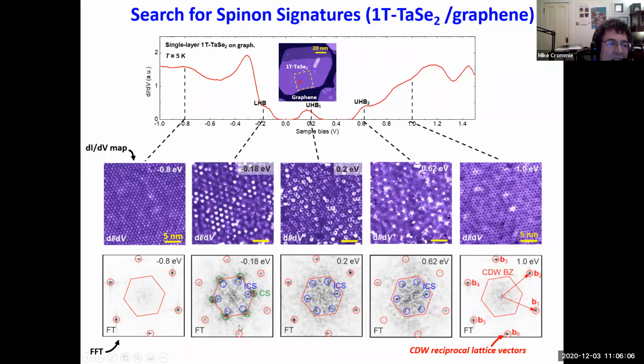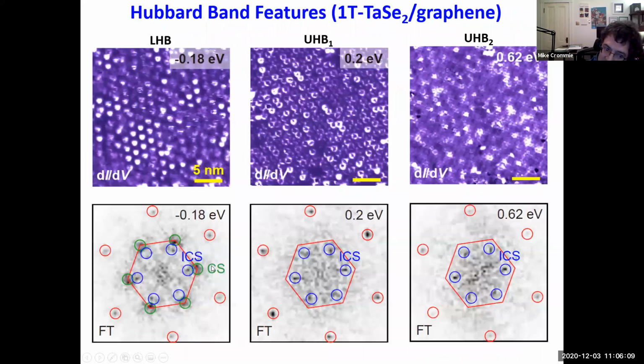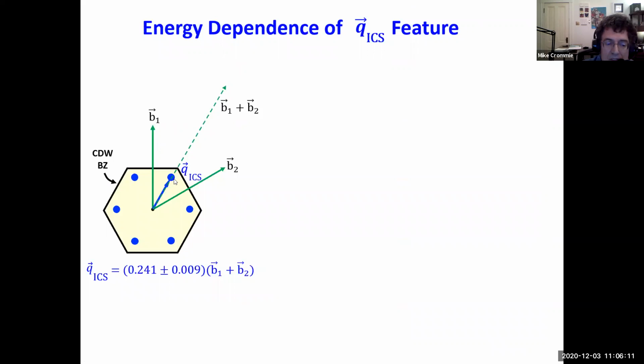Let's take a closer look at it. Here I show in this little cartoon this ICS structure, this blue dot. Oh, it said my internet was unstable. I'm sorry. So this blue dot here is the experimental ICS feature that we see experimentally. I just drew it here in this cartoon, but here below you can see what we measure experimentally. So there's no theory yet. This is just experiment. It's at 0.241 times B1 plus B2, where these B's, remember, are the reciprocal lattice vectors of the CDW lattice.